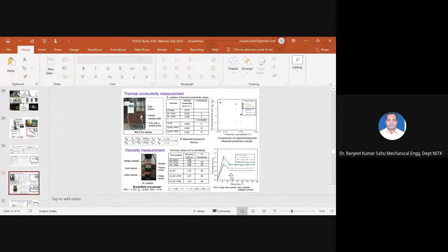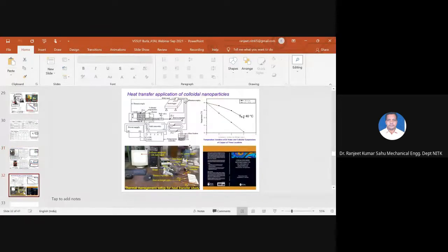Then beyond this, up to 150 second inverse shear rate, the viscosity does not vary appreciably, which indicates the Newtonian behavior of the fluids. But from this graph, it is found that the viscosity of the copper nanoparticles dispersed in various fluids is more as compared to only DI water. So based on that, we have developed an application setup for heat transfer purpose.